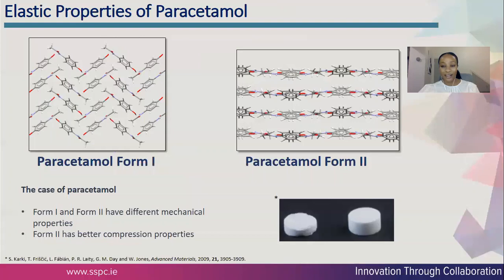A good example of where mechanical behavior can neatly translate to structure is the case of paracetamol. So the two polymorphic forms of paracetamol, form 1 and form 2, show quite different crystal packing arrangements and therefore mechanical behavior. The thermodynamically stable form 1 shows these hydrogen bonded pleated sheets as shown by the image on the left, and the metastable form 2 has parallel hydrogen bonded layers as shown by the image on the right. The layered structure of form 2 facilitates slip via shearing, which then results in improved compaction properties and tabletability properties.